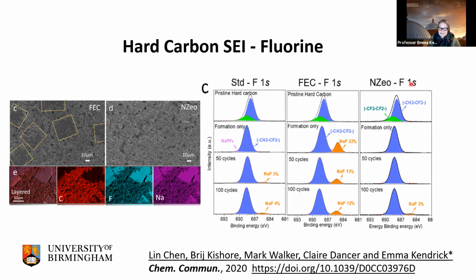And what we found was that the nanozeolite was mopping up things like HF and water. The water reacts with the NaPF salt to form HF, which then forms the sodium fluoride. And by putting the zeolite in, we stabilized the interface by removing parasitic reactions from the electrolyte decomposition. And that's what stabilized it.